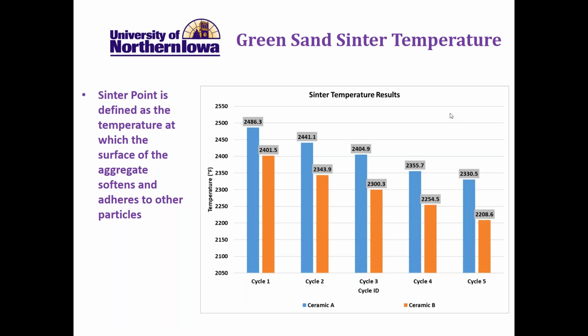So this simulates a foundry being able to use that sand over and over again. We can see a decrease from cycle 1 over to cycle 5 because we are building up some contamination on that sand that was not reclaimed. Previous research has shown us that between cycle 5 and cycle 8, we reach equilibrium, where we no longer see a decrease in the center point of the sand. It also should be noted, this is the same for silica sand or any of the molding aggregates you may be using.